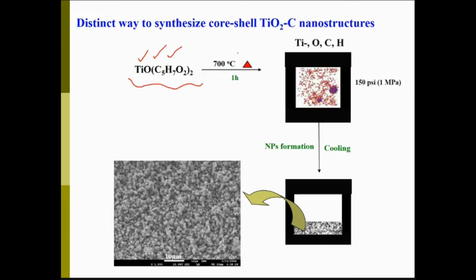So when you heat it up at higher temperature, you are getting a variety of things in a critical phase. That TiO2 can form the TiO2 that you need as a ceramic, but carbon comes and separates from TiO2 and says, I am not going to talk to you anymore because my stability is different than yours, so I will stay away from you. Then TiO2 condenses and makes nuclei. Afterwards, carbon comes around it and hydrogen stays as a gas. Eventually, you get a core-shell architecture, and this is a unique product that you can utilize for